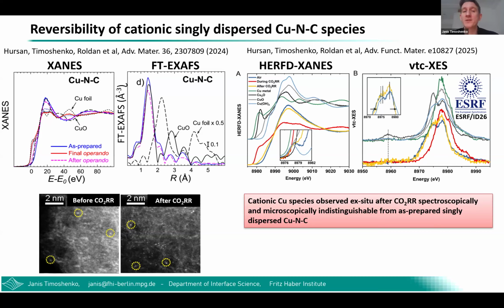And again, it's important to emphasize that it's really a formation of the original singly dispersed sites. It's not oxidation of particles. It's not dissolution of particles. It's not appearance of some new species. We applied different techniques, so the X-ray absorption method, but also more advanced X-ray based methods to study this process. And in all cases, we see that the final state of the catalyst after we remove the applied potential is basically indistinguishable from the original state of the catalyst, where we have these nicely singly dispersed copper sites.